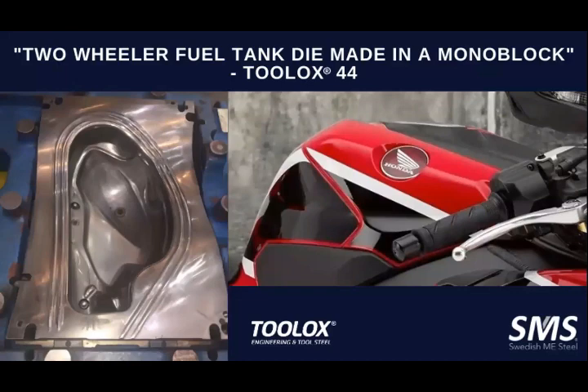This is an interesting application that we did with Toolox. It's also close to my mind, as this was our first major project that we did for an OEM. So as you would see, this is a two-wheeler fuel tank die. The previous solution being casting plus chrome plating. But one issue they faced, not in tool making but in the production, was that after every 50,000 to 80,000 shots, you need to recoat your die which was made out of casting.